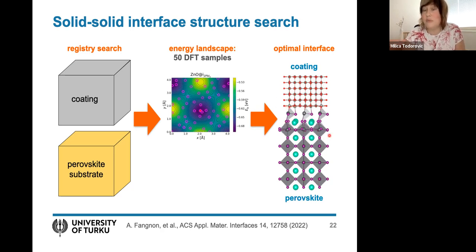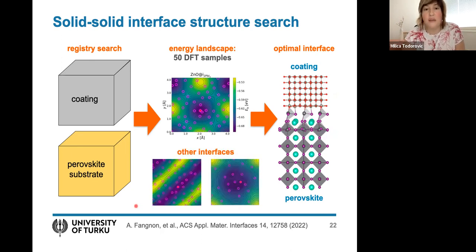And after we did this, we could study the level alignment of electronic levels on the coating and the perovskite. This is important for understanding the charge injection across this interface, which of course is important for a solar cell application. And I want to draw your attention to the fact that with different coatings, you can really obtain different kinds of energy landscapes here between the substrate and the coating. Because this is in two dimensions, very few DFT calculations are needed to just obtain these landscapes. Of course, you have to relax it afterwards.